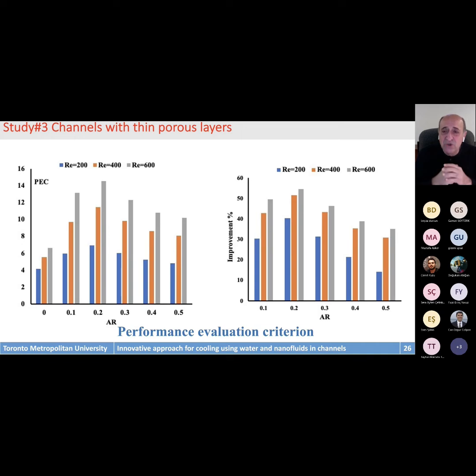So by doing this, we notice from our exercise that the best performance for us is when the aspect ratio equals 0.2, meaning there is a thin layer of porous media around the wall of the channel, and the advantage of it is that it improves the heat enhancement, that's one.